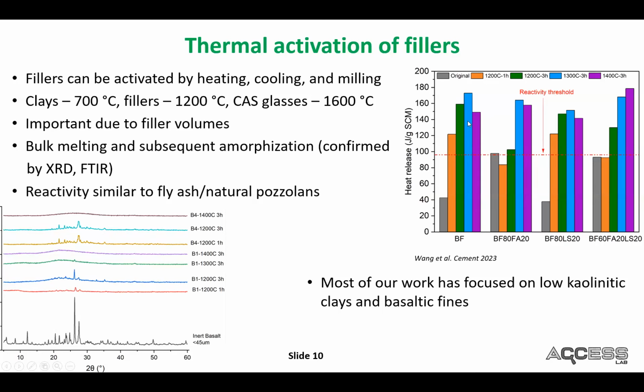Most of our work has focused on low kaolinitic clays and basaltic fines. We find in terms of temperatures that 700 is enough for clays. For clays it's not really melting, it's something else which we won't get into the details of. For these fillers or basaltic materials, we found this melting, or really activation, temperature to be about 1200.